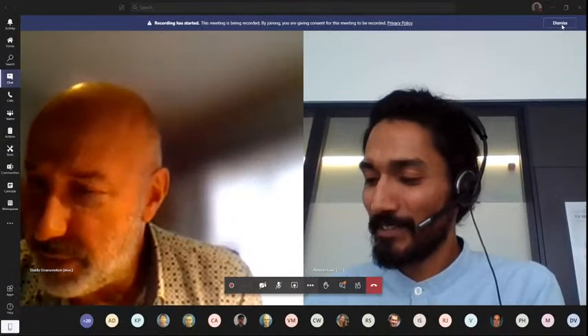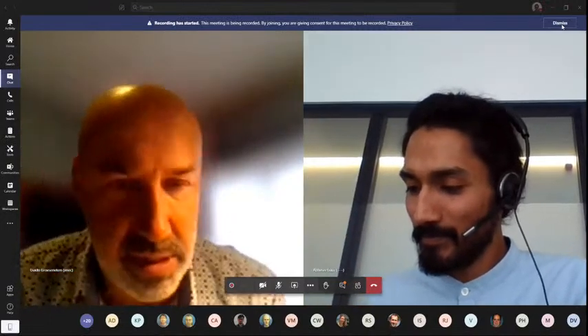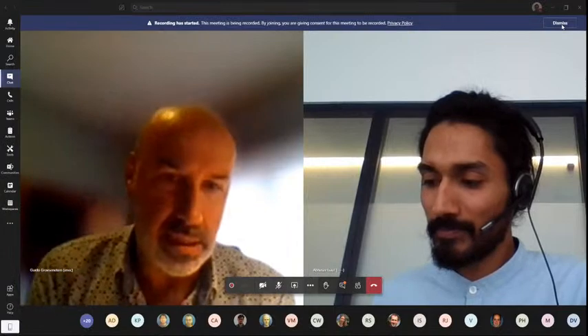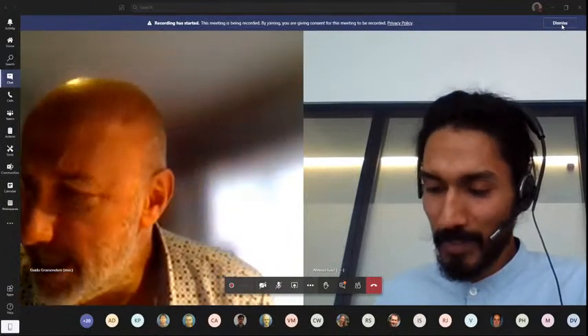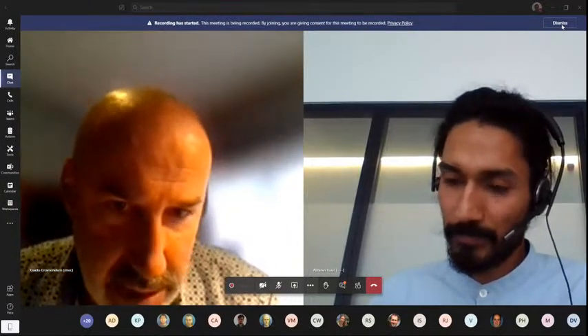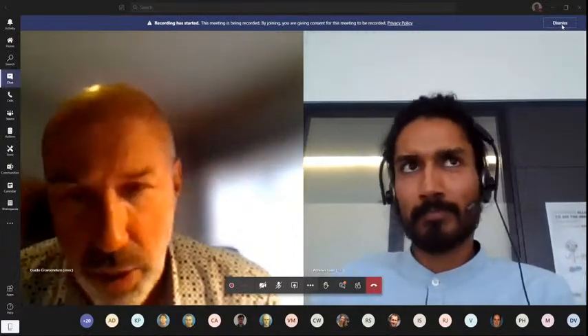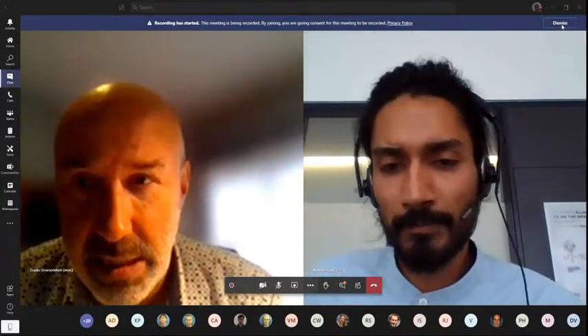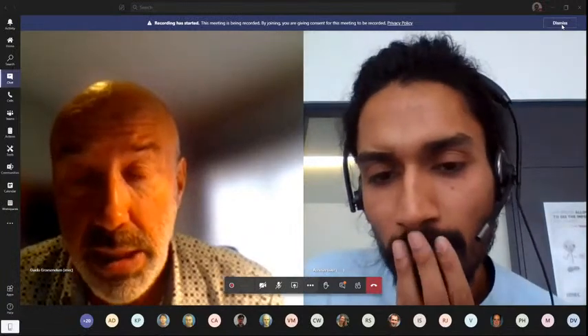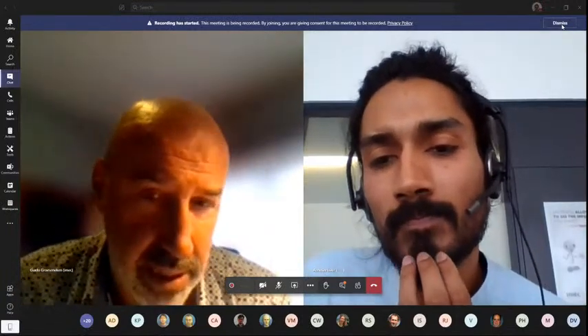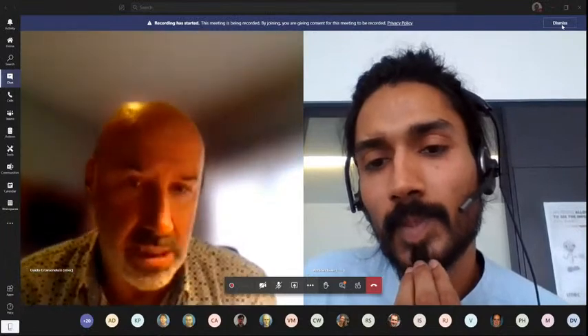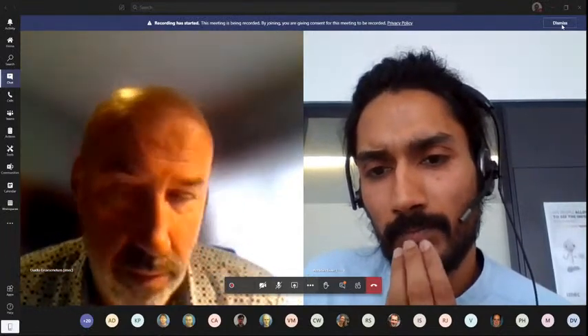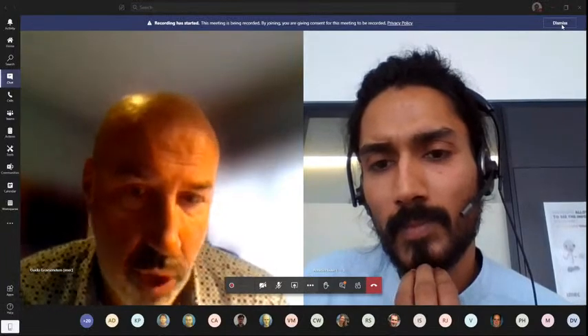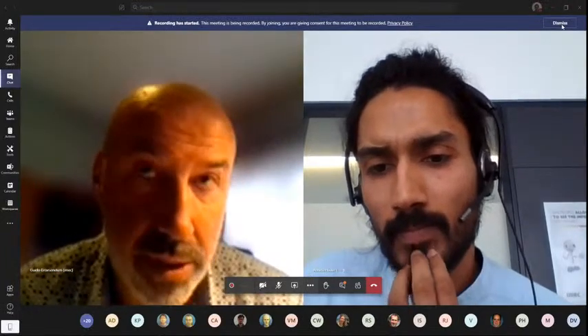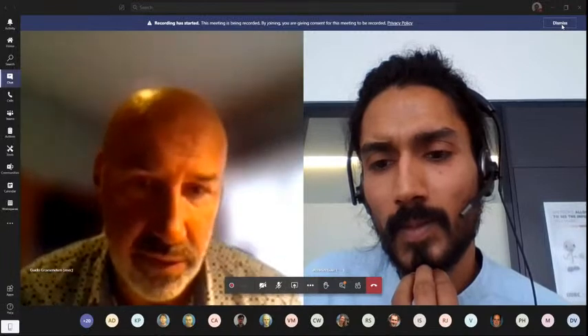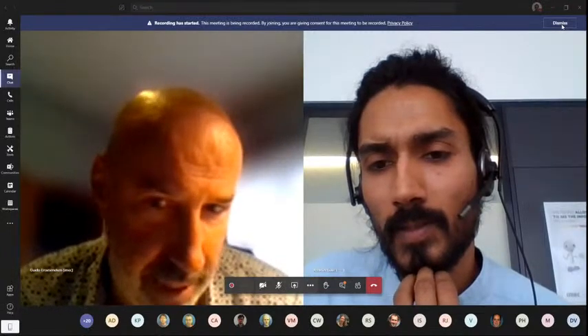And you find that indeed you have this water and carbon residue interface layers that severely limit your capacitance, your performance also. And also the mobility, I guess. The mobility will also be reduced by this. So my question is, how can you get rid of these layers? Is this a fundamental problem, or is this something that is only related to the immature processing at the moment? Do you have some outlook, some perspective to get rid of that interface residue layer?